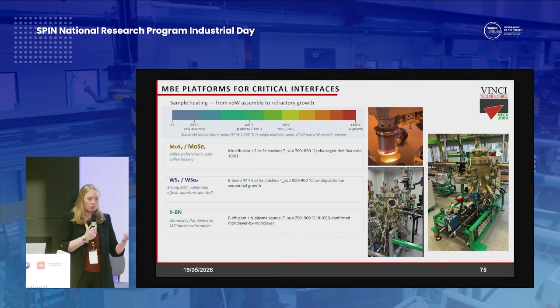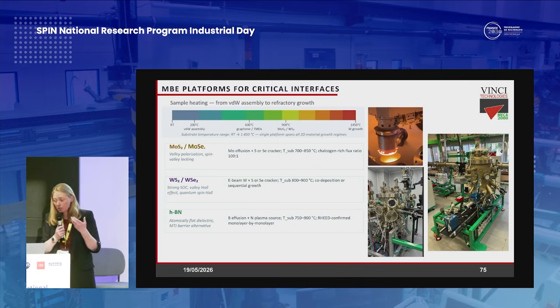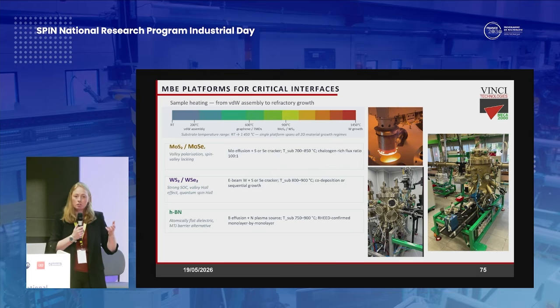The selenium flux as well, using different, let's say, tricks by putting in cold traps or by putting in different types of shielding that can be removable, allows the MBE system to not be subjected to relatively frequent maintenance because these are quite volatile materials that we work with. And for certain of these 2D chalcogenide materials, not necessarily going with a liquid nitrogen cooling. It's not always necessary, and it is an expensive overhead for laboratories.